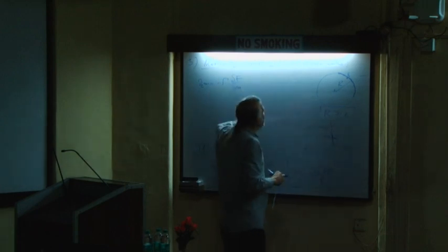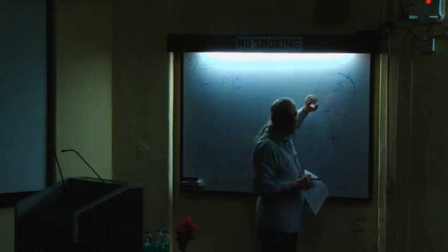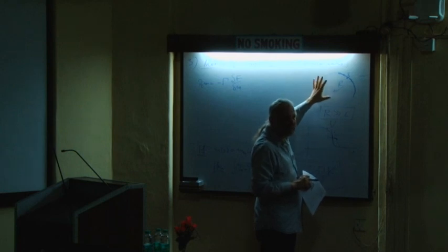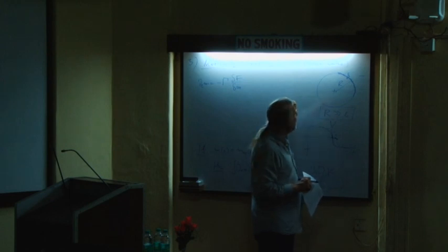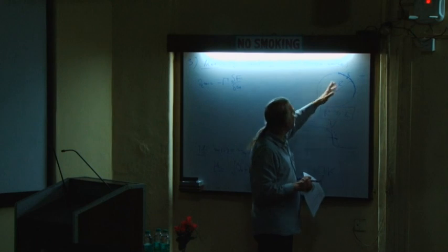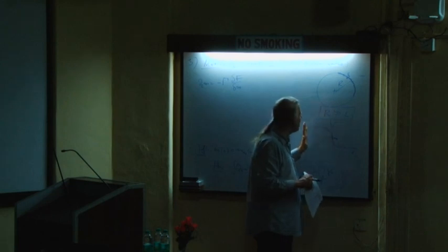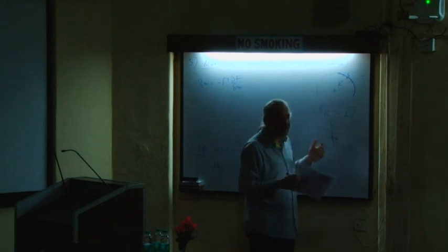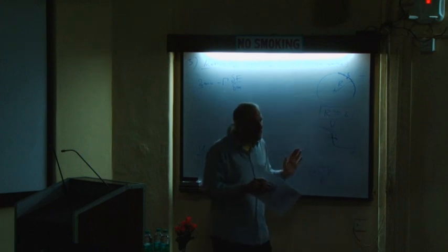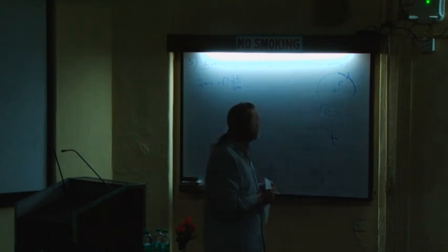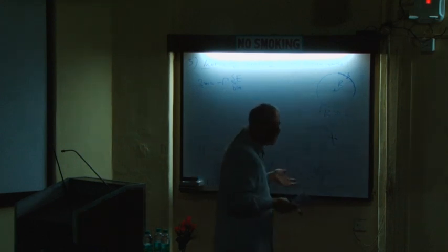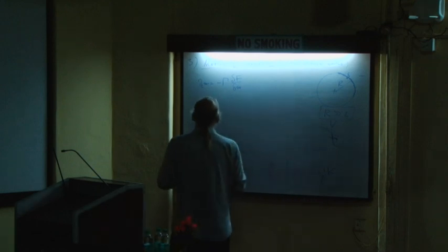So if I have a time evolution here, that means that domain will grow or shrink. Okay? So the interface will move forward or backward. But if the radius of curvature is much larger than this epsilon, I can make the same hypothesis as here. That is, I can suppose that the interface profile is approximately the equilibrium profile and that it will translate with approximately constant velocity. So I can do the same thing as before.